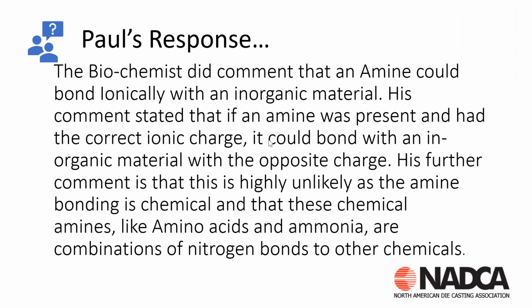So the biochemist did comment that amines can bond ionically with inorganic materials. So they can form an ionic bond, not a covalent bond, with inorganic materials. His comment was that if we had the correct ionic bond charge on our casting, there potentially could be a bond if amines were present. His further comment is that this is highly unlikely, because most amines bond chemically, like amino acids and ammonia, and they don't necessarily bond in an ionic fashion.